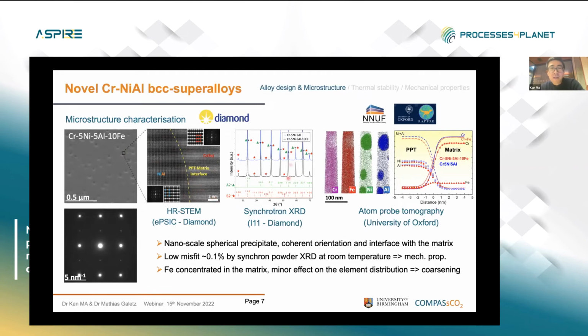It's a microscope center, and we also did synchrotron powder diffraction in Diamond on beamline I11 to measure the lattice parameter of the two phases, the precipitate B2 phase and the matrix phase, to determine their lattice misfit, which is a quite critical parameter for the BCC superalloy design. And the lattice misfit was determined to be about 0.1%, a very low level, similar to the nickel superalloy, which is an important design factor in this system.